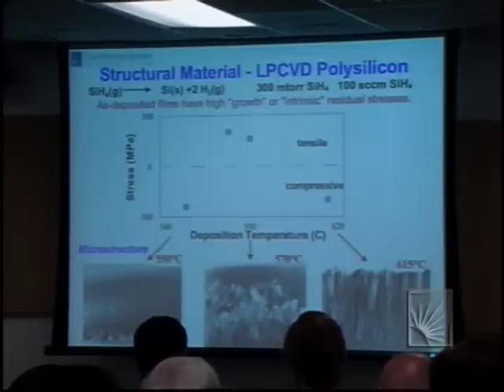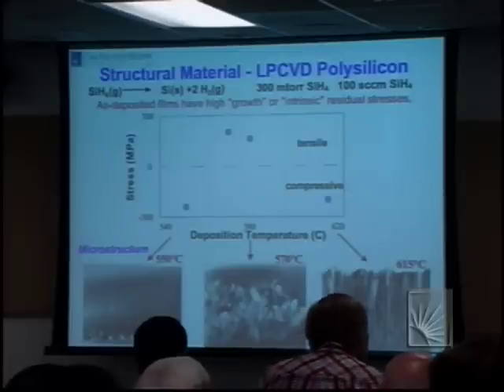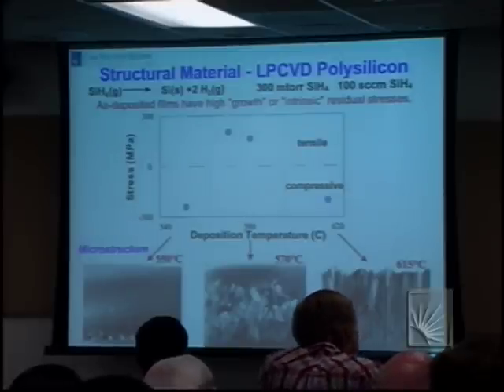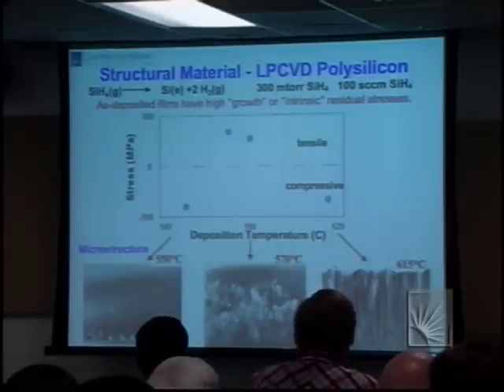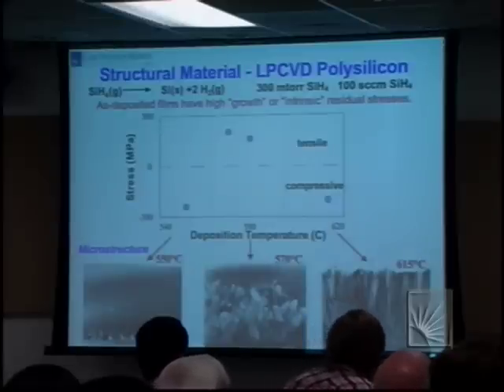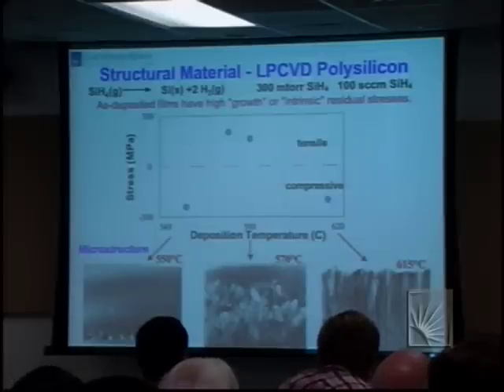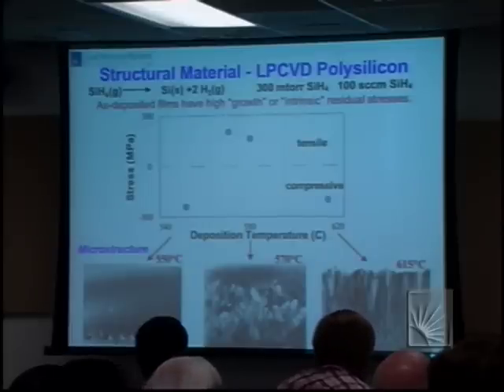And it's curious that at the low temperature end of the regime and at the high temperature end of the regime, the stresses are compressive and of significant magnitude, a few hundred megapascals. But in the intermediate temperature regime, the stresses are also significant, but opposite in sign, they're tensile. And it's relatively straightforward to understand the origin of these stresses.